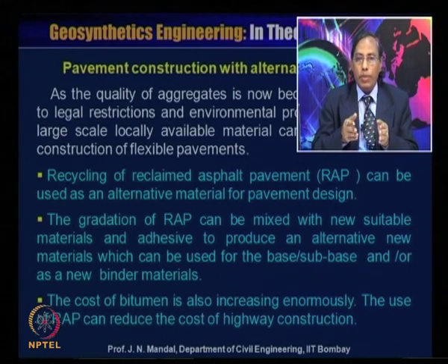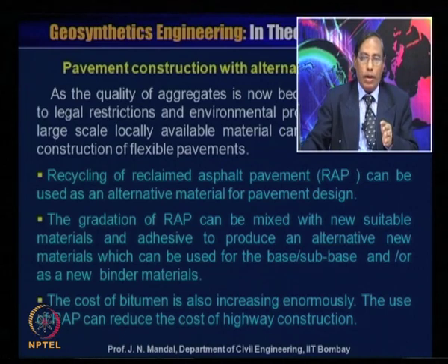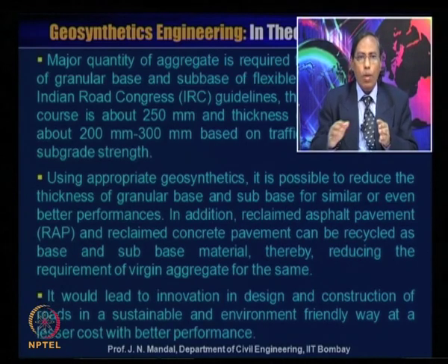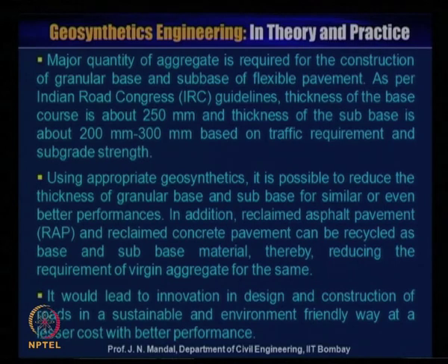which can be used for the base or sub-base and or as a new binder material. The cost of bitumen is also increasing enormously. The use of RAP can reduce the cost of road construction. More quantity of aggregate is required for the construction of granular base and sub-base in flexible pavement. As per the Indian Roads Congress guideline, the thickness of the base course is about 250 millimeter and the thickness of the sub-base is about 200 to 300 millimeter, based on traffic requirement and sub-grade strength.